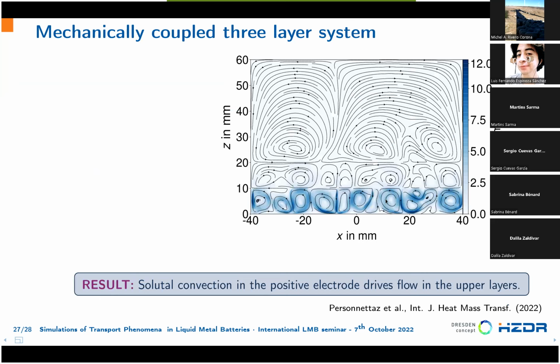And if we look at what solutal convection is able to do in the other layer, we see that solutal convection is able to drive a strong flow in the electrolyte. So not only the positive electrode, but the electrolyte is now mechanically coupled, and flow is generated there. And a weaker flow is also transferred to the negative electrode on top. So we have a momentum transfer across the layers. In this simulation, we are not solving heat transport, only solutal convection in the bottom layer and mechanical coupling and fluid flow in the other layers.